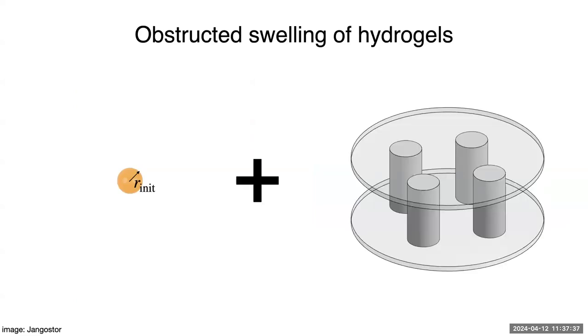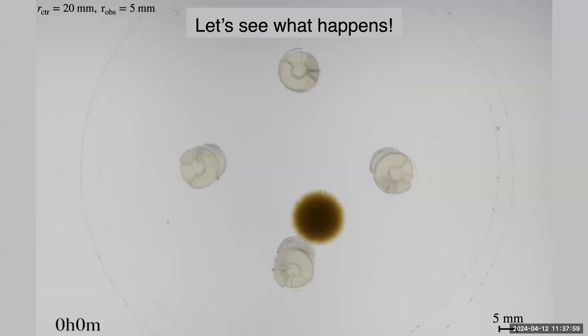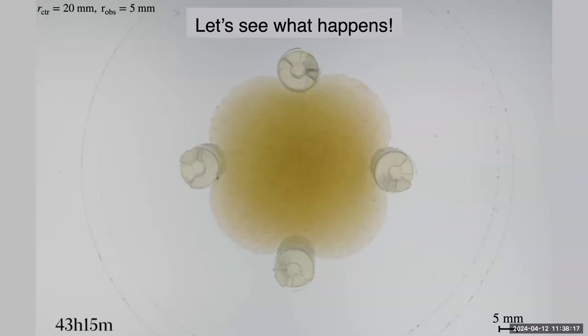So we have our expansion. Now we just need our obstruction. What we do is we take our hydrogel bead and we put it in an obstacle array. Here we have 3D printed obstacles so we can tune their size and shape and we've fixed them to acrylic plates. So now we conducted the simplest experiment that we could imagine. What we do next is we take this hydrogel bead, we put it in the center of the obstacle array, we put a camera focused on the top plate, and we just watch and see what happens. We have this hydrogel swelling. Initially, it's a little unfocused since it hasn't made contact with the top plate yet. We see these really beautiful cusps, these petal-like lobes. That's a transient structure that's well understood. As water travels through the hydrogel, the outer portion swells before the core, leading to these compressive transient stresses in the formation of cusps.